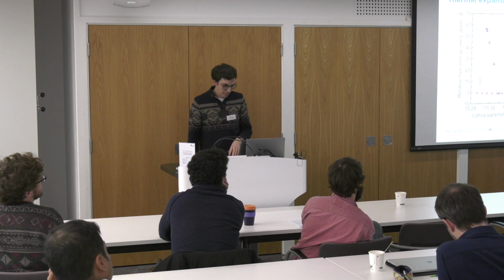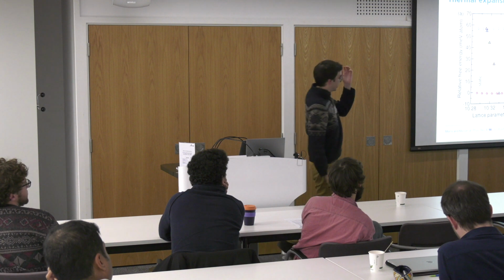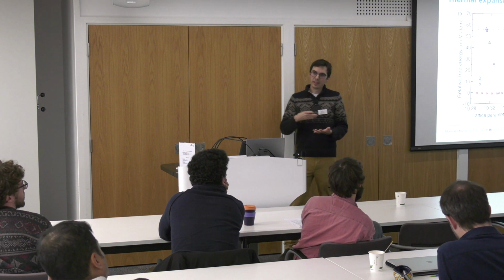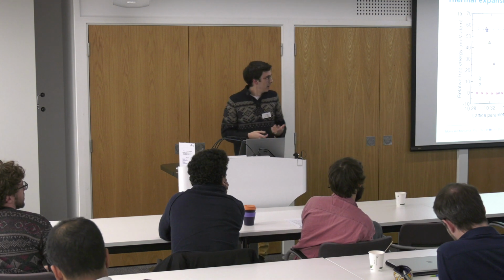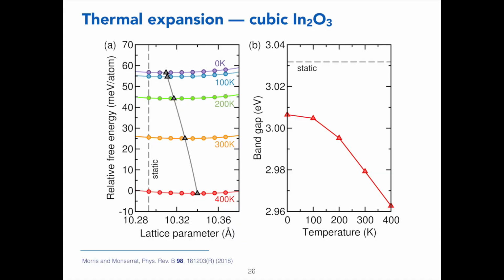Just as another reminder, in all these calculations, although I'm focusing on dynamic disorder, that is the interaction between electrons and phonons, temperature also has another effect, which is that of thermal expansion. So here I'm just showing an example of what happens in this particular case due to thermal expansion. What we do is we calculate the temperature-dependent volume by minimizing the free energy of the material at a given temperature, and then we can also look at the changes, say, in the band gap as a function of purely thermal expansion.